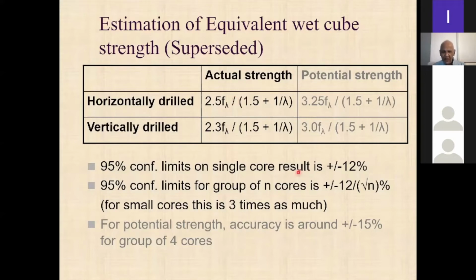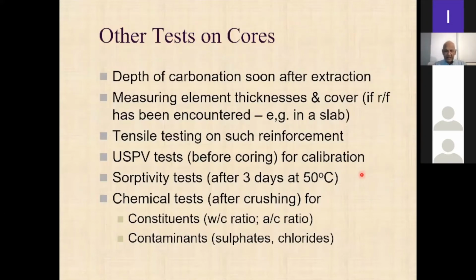Now, if you want 95% confidence limits, you can say it's plus or minus 12%, right? We don't really use those very much if you use cores directly, right? Right now, like I said, once you take a core, try to do all of these things in the core, because if you are doing an actual structural assessment, by the time the structure is in midlife, you're not worried about the concrete quality and whether the contractor supplied you the correct concrete.